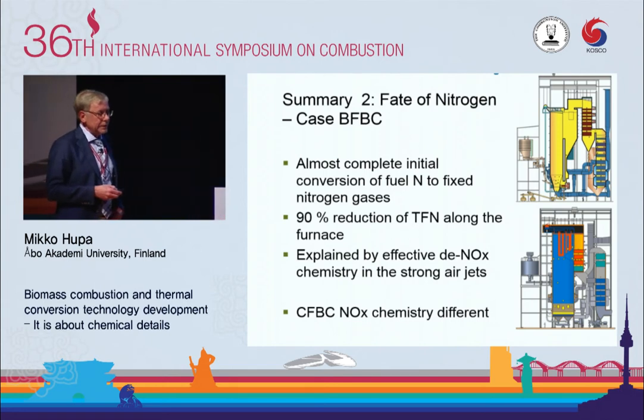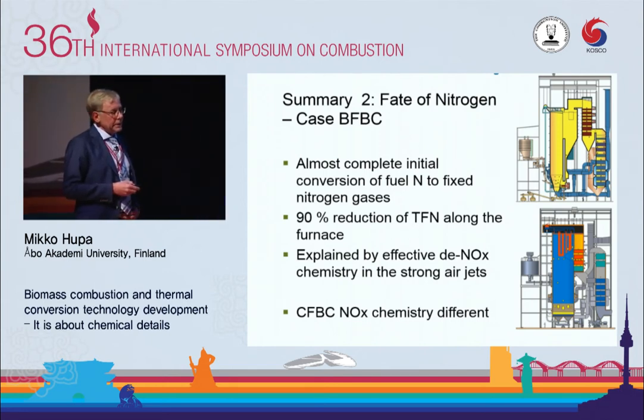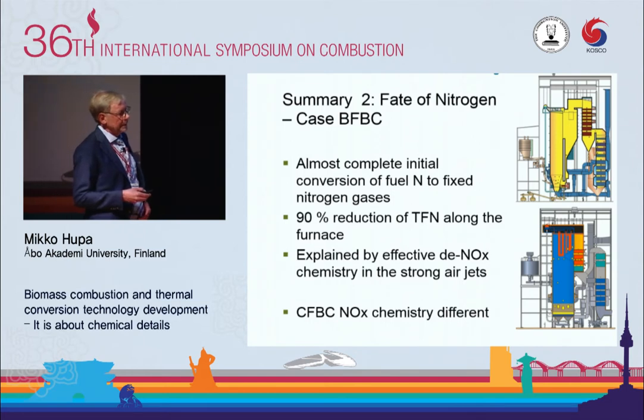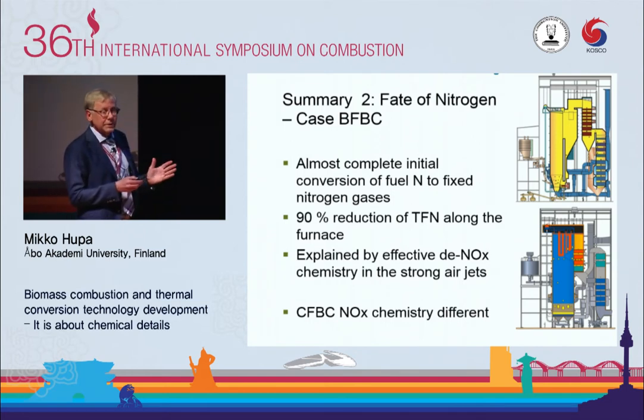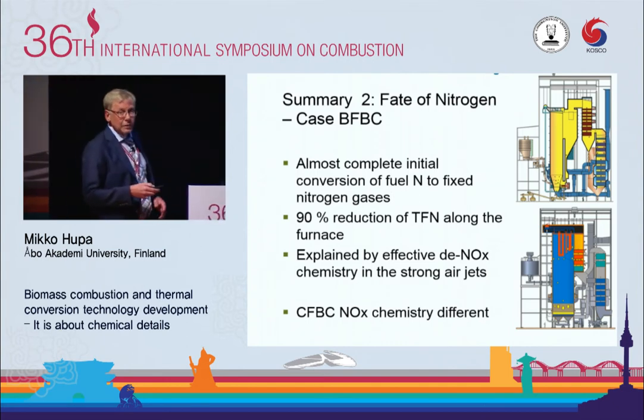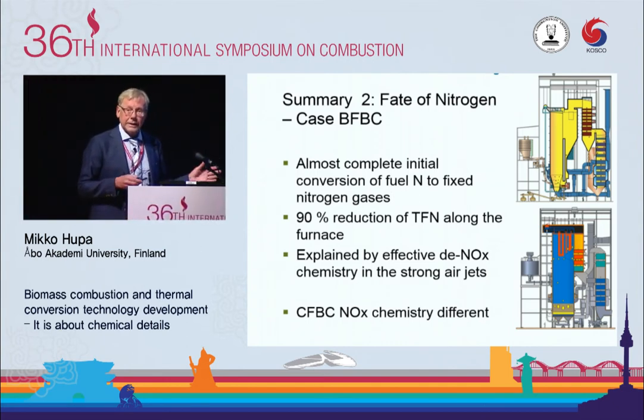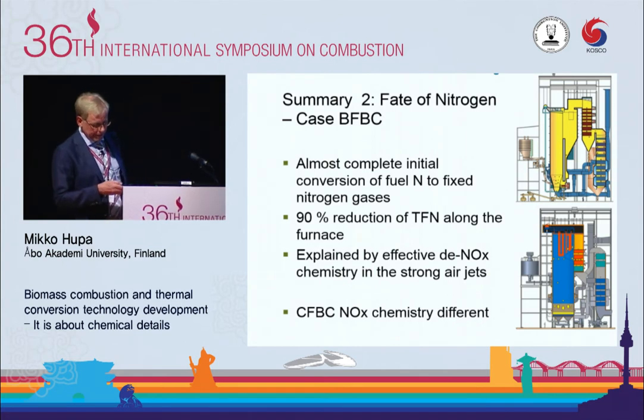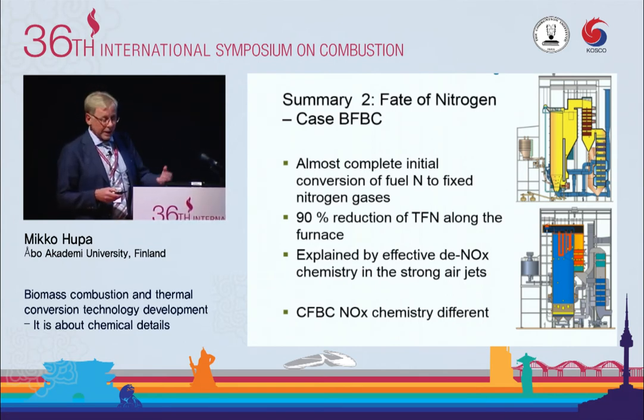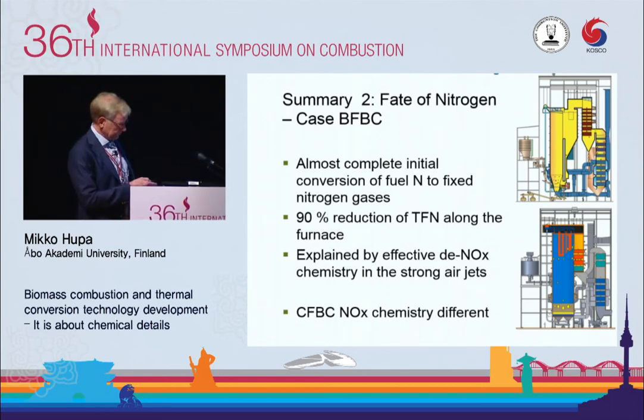Some summaries of this. Almost complete initial conversion of fuel nitrogen to fixed nitrogen gases in the lower furnace, but then 90% reduction. And we think that this is a special feature of this new air feeding technology. For circulating fluidized beds, the nitrogen chemistry is very different, but I cannot go into that. There, the char reactions start playing a role.